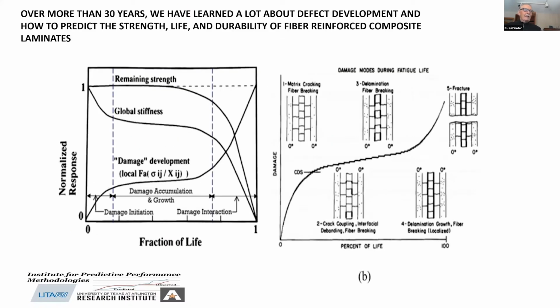Now, I suspect that by now many people who are watching have seen these diagrams because they've been used the world over for a very long time. It is our imagination of the damage development as a fraction of life on the left-hand side, normalized fraction of life. And you can see this sweeping curve, bottom left to top right, which indicates damage develops at the beginning of life, micro cracking typically, matrix cracking. Then things level off quite a bit, and then there's this acceleration at the end.